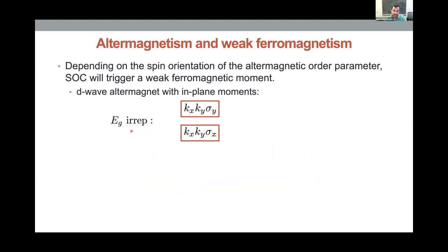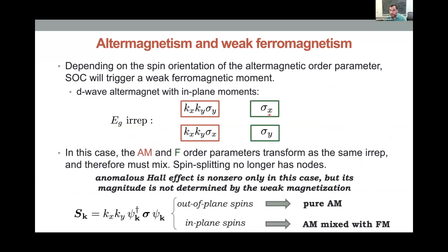Now, the other important effect is that if I assume that the spin is pointed out of the plane, but if they point in the plane, in this case, now this order parameter transforms as the Eg irreducible representation, which is the same as a ferromagnetic moment. And that means that when I turn on spin-orbit coupling, if my altermagnetic moments are in the plane, at least in this situation, they will induce a ferromagnetic order. Okay? Now, by the same token, that same symmetry that allows ferromagnetic order to exist is also going to allow the anomalous Hall effect to be present. It's very important to point out that the anomalous Hall effect is actually not determined by the magnetization, but is just enabled by the same symmetries that enable a finite magnetization. In fact, as shown by Libor and his collaborators already in 2020, they will have a very large, let's call it incipient, anomalous Hall effect just from the altermagnetic band structure. Okay.